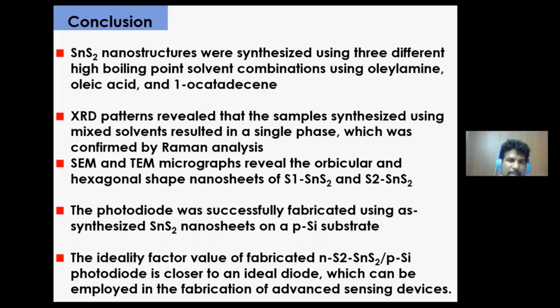SEM and TEM micrographs reveal the orbicular structure and hexagonal shape nanostructure for S1, SnS2 and S2, SnS2, so we can differentiate them using SEM and TEM analysis. The photodiode was successfully fabricated using synthesized SnS2 nanosheets on a P-type Si substrate. The ideality factor value of the fabricated N-type S2, SnS2 on the P-type silicon photodiode is somewhat closer to an ideal diode.